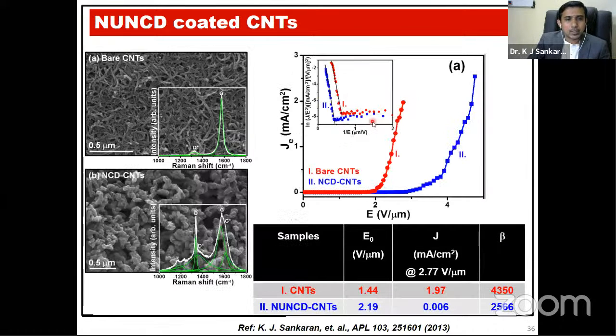Again, in the beginning, I told you that carbon nanotubes and graphene achieve a low turn-on field, but they cannot withstand a long lifetime, even at high voltage. But when you coat the NUNCD films on the carbon nanotubes, this is the NUNCD film coated on the carbon nanotubes, and the Raman spectra show the presence of diamond coated on the carbon nanotubes, and you can see that the turn-on field is really high as compared to the carbon nanotubes.